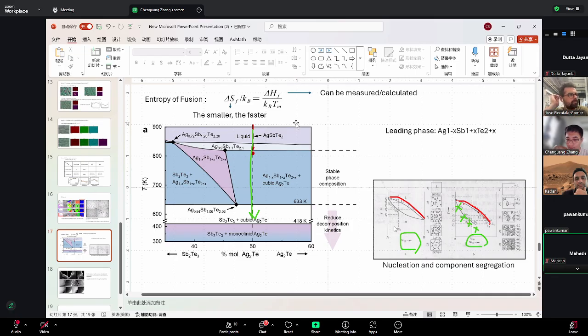Is it cooling data or the warming curve actually? Cooling. This is cooling. Cooling, then okay. In equilibrium, cooling and heating will be the same. In non-equilibrium, for sure, they will not be, right? Then yeah, different temperature XRD will work actually. No, how do you cool it? You can stabilize the temperature, right? At that temperature in high temperature XRD.